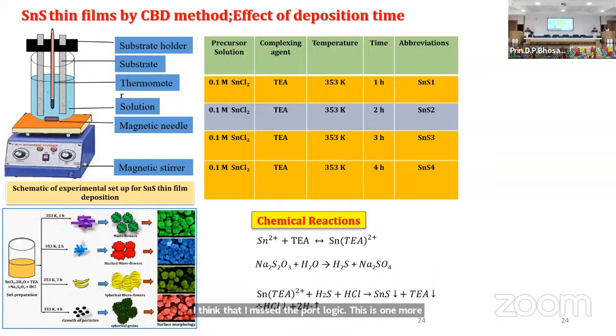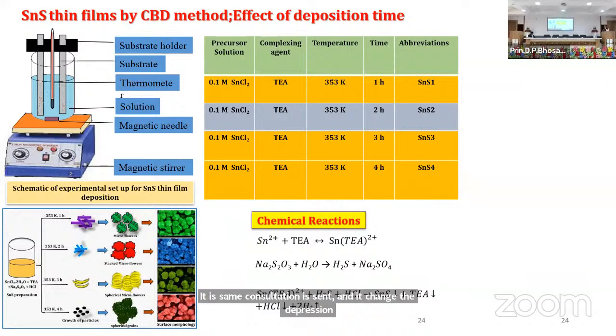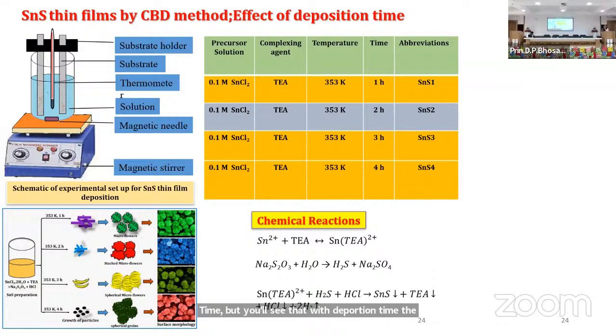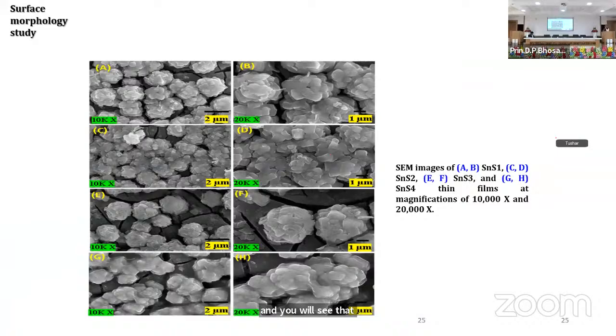This is one more material, tin sulfide, SnS. This time you can see the deposition time. The deposition time is different. You keep the other parameters constant. The temperature is constant, the complexing agent is the same, the concentration is the same, and you change the deposition time. You will see that with deposition time, the morphology changes. Of course, I'm not going into the reaction kinetics, what happens initially and how the morphology changes with time. But we assume that the morphology changes with time, and this is the morphology we get. Of course, not all morphologies are good for our applications, but we can find which is the best one for us when we study a particular material.